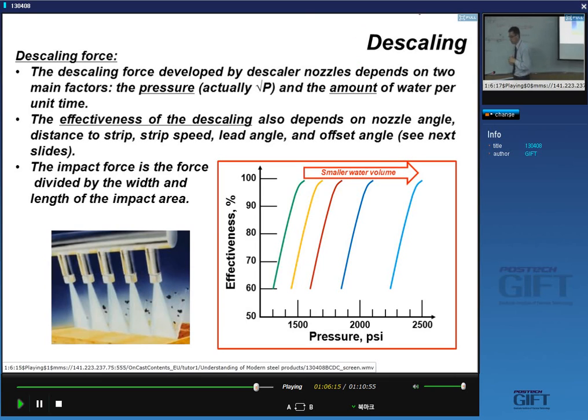So, for instance, if you look at the effectiveness of the removal of the scale, it increases with pressure. And if you use less water, which is something you want to do because it has an impact on your operating costs, with smaller water volumes you have to increase the pressure. That's why the trend in descalers is to make them more compact, higher pressure and less use of water. Descaling force,